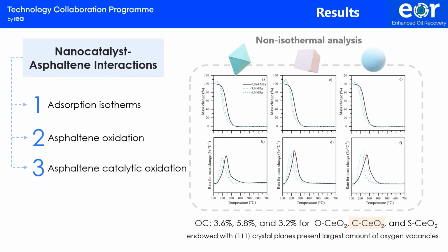Also, the main decomposition temperature peak is observed at low temperatures close to 190 degrees Celsius at 6 megapascals for the cubic sample, and increases in a lower degree for the octahedral and the spherical.